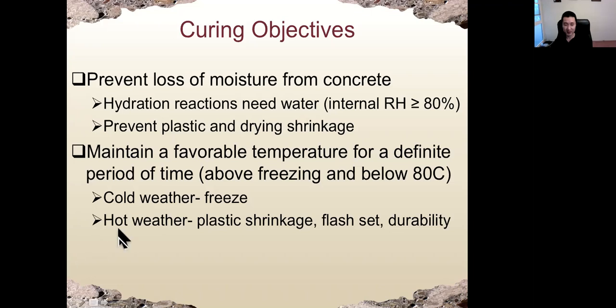The temperature also cannot be too hot. In hot weather, shrinkage will increase and the concrete may crack, or it could cause problems such as flash set, where the chemical reaction in concrete changes due to high temperature and the concrete may set in a few minutes - that is also not good. There are also durability issues when concrete temperature is too high, such as delayed ettringite formation, which we'll talk about in a moment.